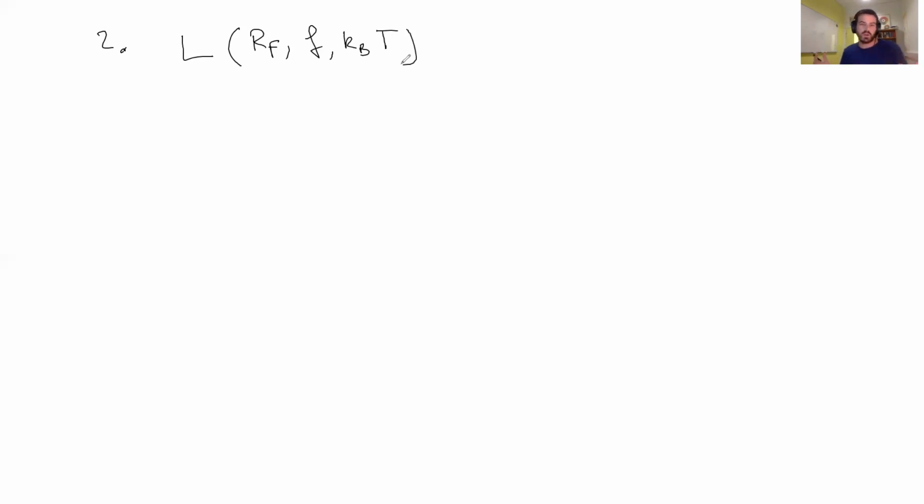So in very general terms, by dimensional analysis, I'm expecting the length to be a function of the initial radius, the force, because I'm pulling on it, and the fluctuations induced by the temperature. And so in scaling analysis, here I have 4 variables and 2 units, length and force. The final one, the energy, is a combination of the 2 previous: it's force times length, so it's not an independent unit. So you have 2 independent units.